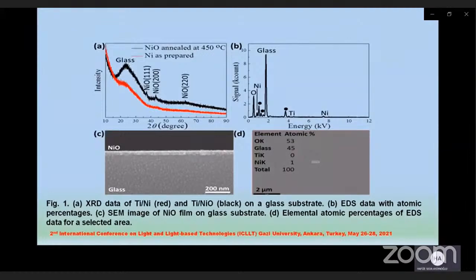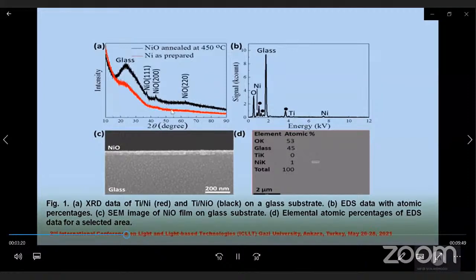We prepared two samples on a glass substrate: 50 nanometer nickel thin film as a control sample and oxidized nickel film to form nickel oxide film on glass substrate. The XRD results of these samples are presented in Figure 1a. The as-prepared nickel, red line, exhibits amorphous phase formation rather than crystalline nature.